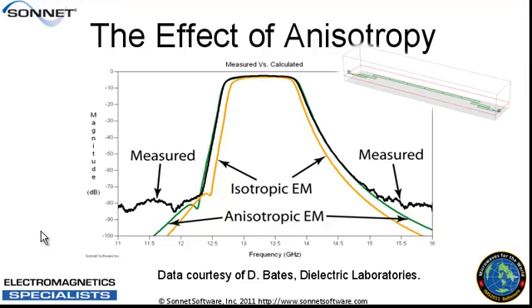So why is that? It's because of coupling and center frequency having different dependencies on permittivity. The center frequency of this filter is dependent on the vertical electric field, because it's dependent on the resonant frequencies of the resonators. The bandwidth is dependent on the coupling between resonators, which is mostly horizontal electric field. So if you sweep the isotropic dielectric constant, some results would have the bandwidth right and some would have the center frequency right, but none would have both.